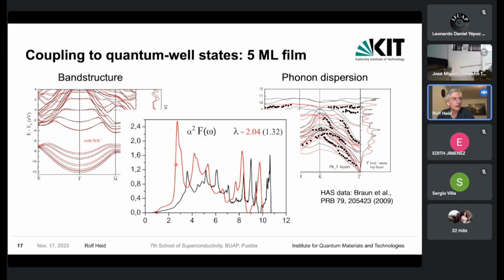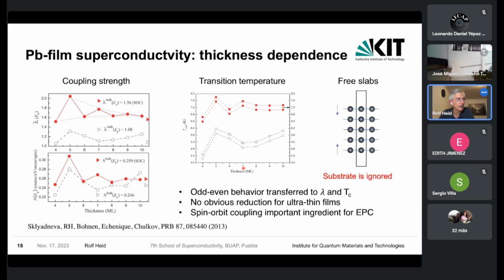And what you can see is the overall coupling strength is actually 2, which is even larger than in lead bulk. And one of the features we have been analyzing in more detail comes due to the enhanced density of states at the Fermi level due to the presence of these quantum well states. And the next slide shows now a kind of summary of several of these calculations.